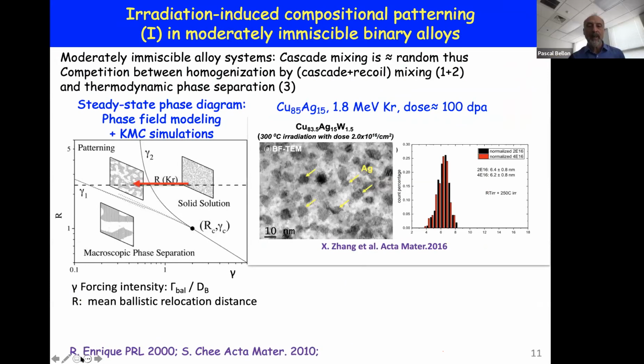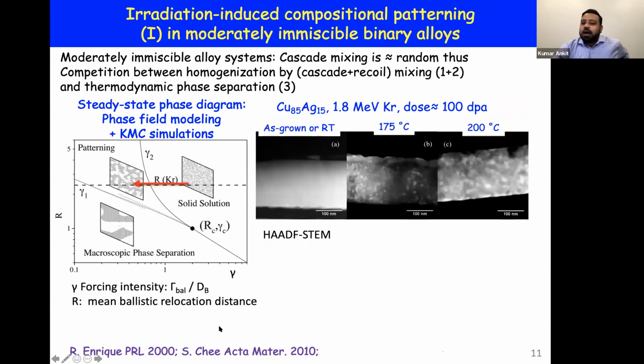So I had a question about this. I presume this was done for 2D microstructure, or rather, I presume this was a phase diagram generated out of the phase field and KMC modeling approach. On the left hand side, those boundaries were initially obtained with a 1D phase field model. Then, as I showed you later, we used MOOSE to do 2D, and now we do 3D. And the KMC simulations are 3-dimensional.